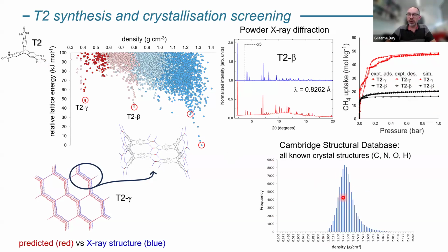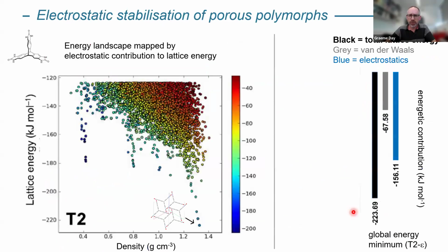A nice thing to point out is if you look at all the molecular crystal structures in the Cambridge Structural Database which have the elements that we have in our molecules that we looked at in this study, that's the distribution of densities. That's the density of the structure we found in this computation-led approach. So we're finding things that were really out of distribution of normal things that we find from most structures in our experimental databases.